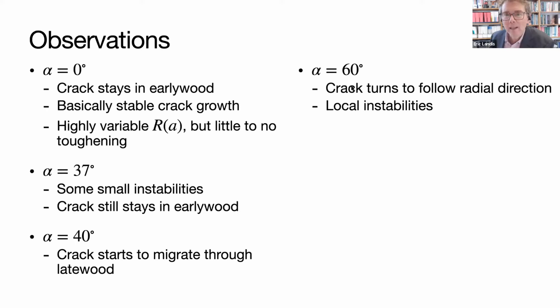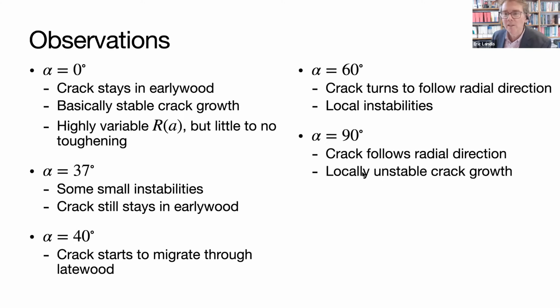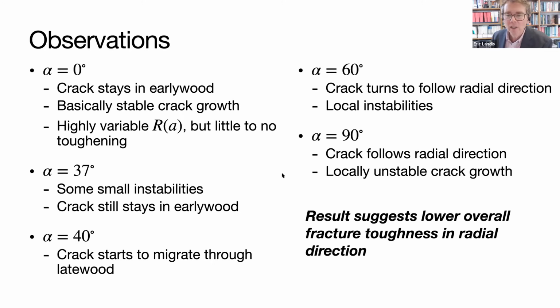And as we get even higher alpha, now we start to follow the radial direction, and that is accompanied by local crack growth instabilities. And finally, when we go in the purely radial direction, we have locally unstable crack growth, and the crack will just propagate in that radial direction, which suggests that, in fact, the radial direction of crack growth has lower overall fracture toughness than the tangential.